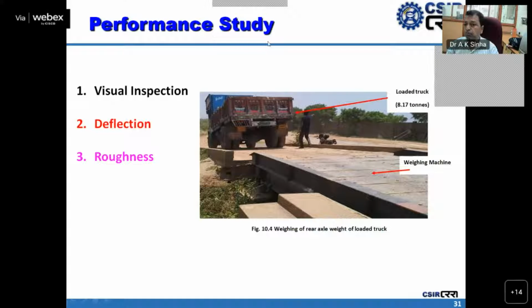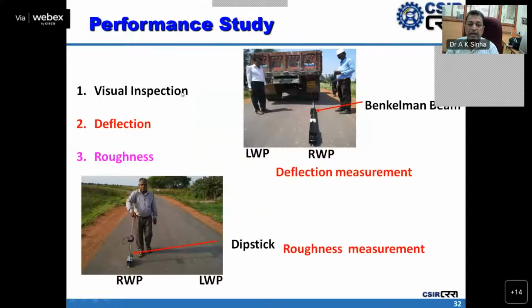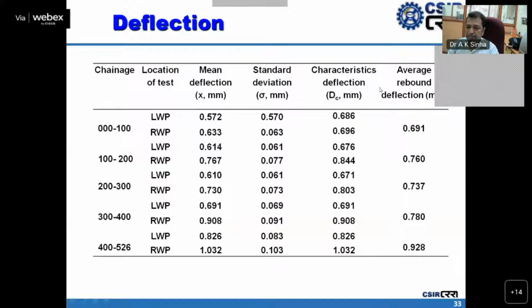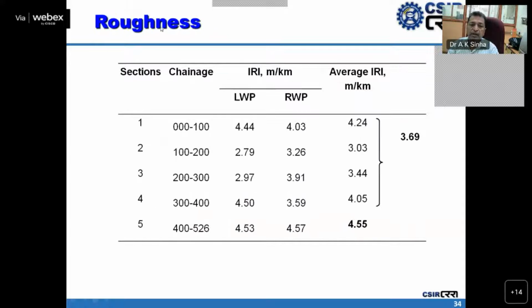3 years of performance monitoring was carried out using different equipment, measuring deflection, roughness, and visual inspection for 3 years. This is the pictorial view of the measurement of deflection under the right wheel path and under the left wheel path. And this is the roughness measurement using a dipstick on the right wheel path and left wheel path. It was found that the rebound deflection of all sections is comparable to the conventional section. Similarly, the roughness obtained was also comparable to the conventional section.